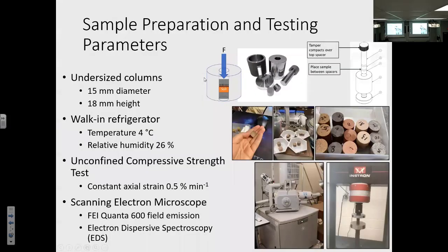So, sample preparation. As I mentioned several times already, one of the biggest hurdles that we had to face for this project was simply the lack of enough simulant. If you've ever been to a civil engineering lab, they make massive columns. Their sample sizes are huge, like 2 inches by 4. That's like a standard. Whereas for us, there is no way we had enough materials to make such large samples. So we went with undersized columns, and I mean tiny. We were making columns that were 15 millimeters in diameter and 18 millimeters in height. You can see just how small they were from these images.